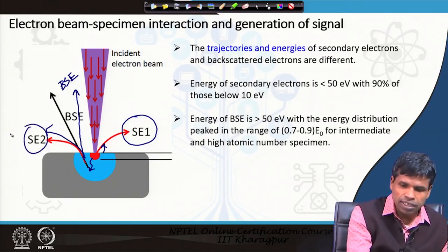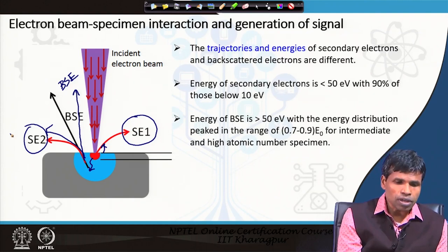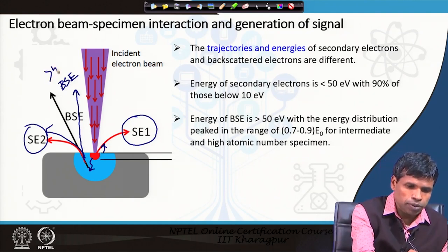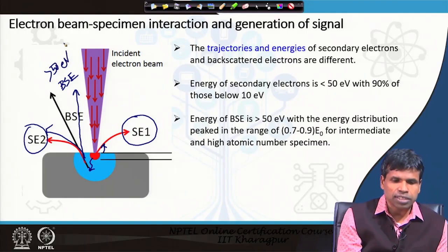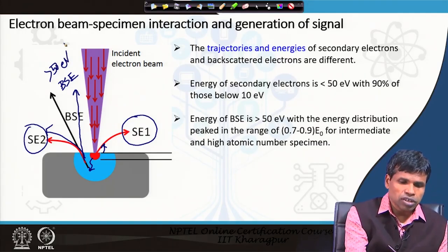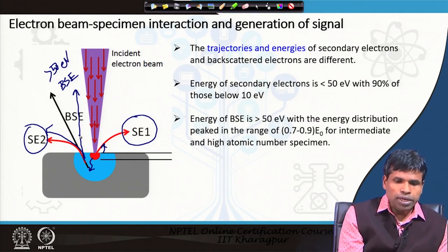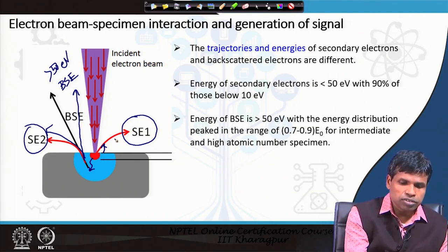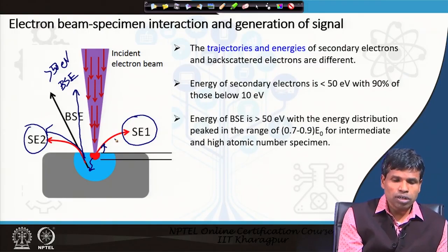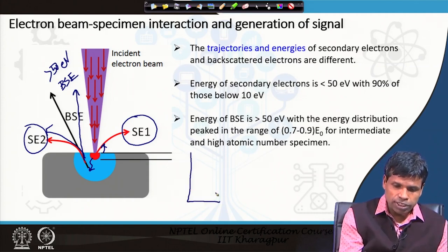These also have energy less than 50 electron volts, but backscattered electrons have energy greater than 50 electron volts, and their trajectories are certainly different. Backscattered electrons are emitted towards the electron beam with a larger takeoff angle. On the other hand, the secondary electron takeoff angle is small and their trajectory is different. So, this is what we have discussed, and we have also discussed that the secondary electron yield or secondary electron coefficient, that is delta,